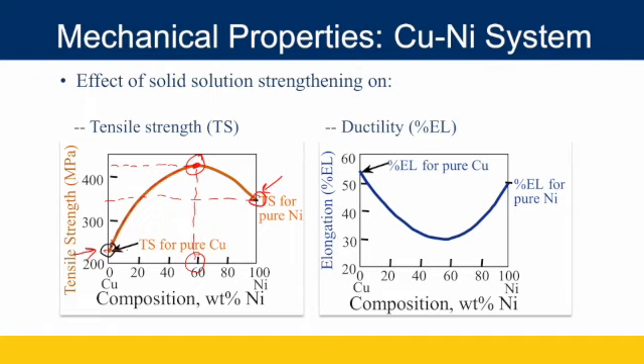Okay, but again, as we increase strength, we always lose what? We always lose ductility. So the ductility of pure copper is about 55%. Ductility of pure nickel is about 50%. At the maximum strength of the two materials, about 60-40, the ductility drops to 30%. So we maximize strength, we always sacrifice ductility. Okay.